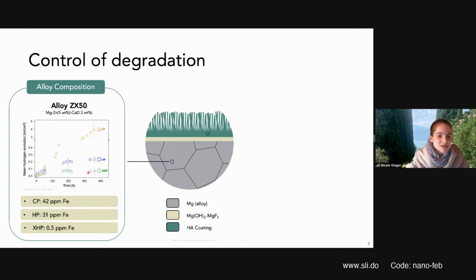So this was not known at the time of Peyer, and now you also know why the implant of this poor boy was degrading so quickly: because Peyer was screwing it on with iron screws, and this was causing galvanic coupling, and the magnesium was corroding like crazy fast.